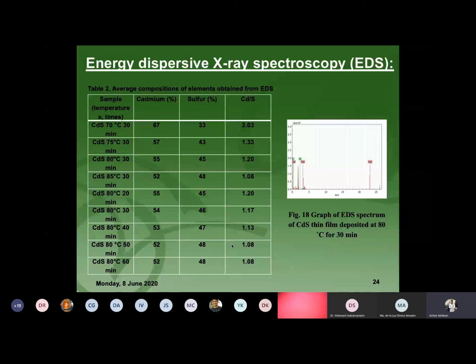We checked that the cadmium content decreases at higher temperature and time, while sulfur ions increase toward stoichiometric compositions. From figure 18, the presence of cadmium and sulfur can be seen from the EDS spectrum of the CdS thin film.